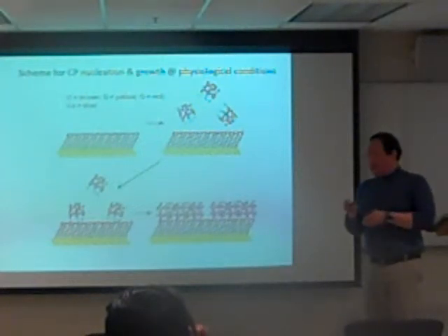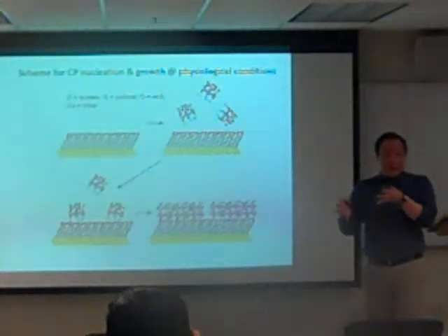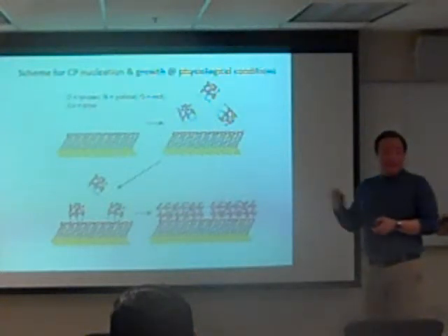This is also supported by the fact that if you took a laser pointer and shined it into the solution, you would see a scattering of light from the Tyndall effect, meaning that there's a formation of those critical clusters prior to deposition on the surface. So at least the experimental evidence is consistent with this critical cluster nucleation mechanism.